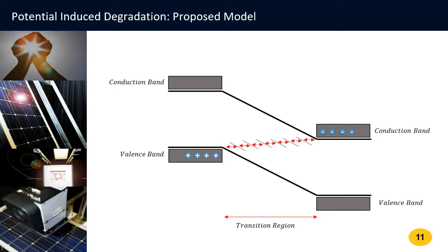When the material gets adequately saturated with these defects, it will create additional energy levels within the band, which provides a hopping-like mechanism for electrical conductivity. That is an ohmic-like response at these localized points within the cell. Very technical, but along those lines.